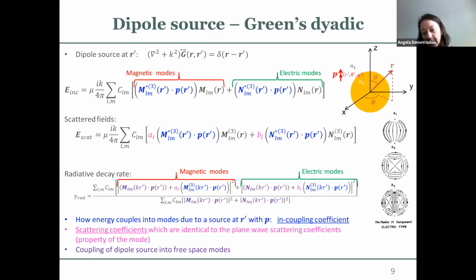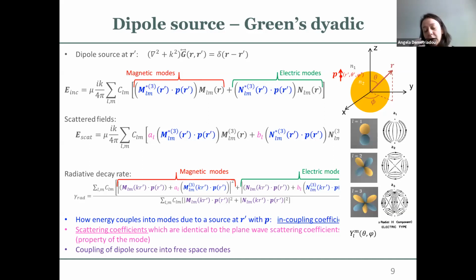And from Mie theory, and this is taken from Bohren's book, the scattering coefficients can give you the normal modes of the system. And the first 3 electric ones, so in our case the plasmonic ones, they look like this. And they are quite relevant to the spherical harmonics, the profiles of the spherical harmonics. So I plotted them here. These are just some pictures of the spherical harmonics that I took from the internet. And you can see that each pole of the spherical harmonics gives you the pole of your Mie mode, the plasmonic mode within the spherical nanoparticle. So you've got a plus minus, you've got a plus minus, and so on. And there are quite a few more modes later on.